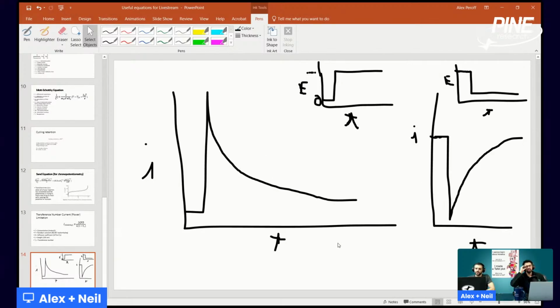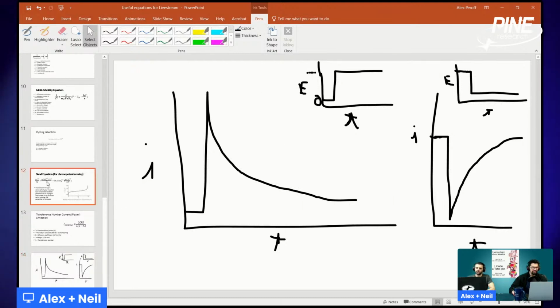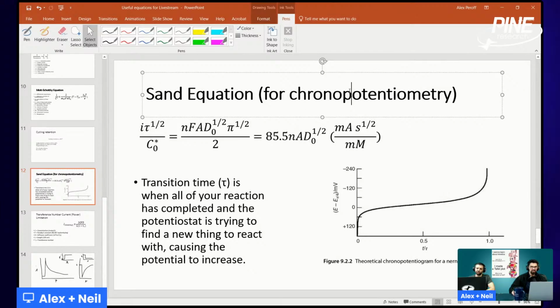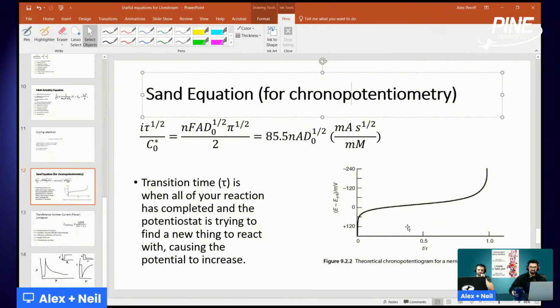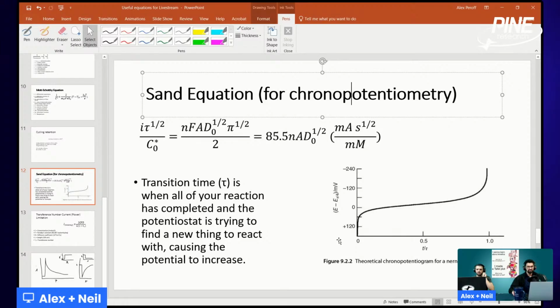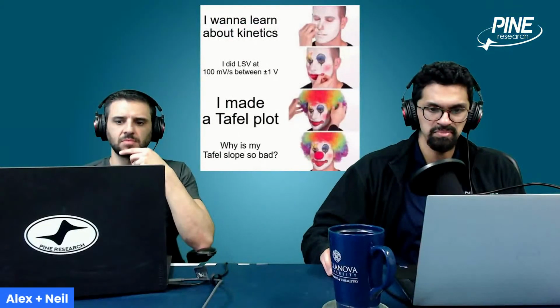In looking at chronopotentiometry, where you set a constant current and then you measure the potential, you can get slightly different looking data. But generally speaking, the Sand equation describes most of the response for a chronopotentiometry experiment, where the potential difference between E and, in this case, E to the tau over 4, is relatively linear. But then all of a sudden, at these limits, where you've given it enough time, it starts to go way up or way down. So again, for a theoretical Nernstian process.